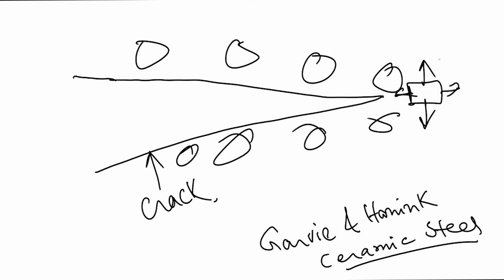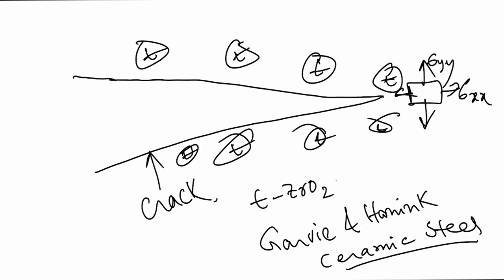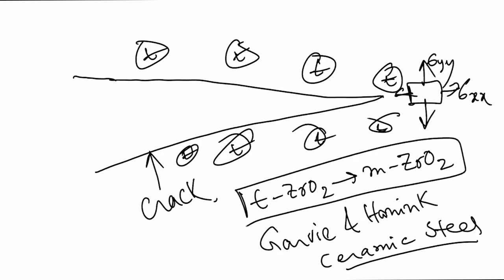Now in the crack tip stress field, suppose this is sigma xx, this is sigma yy and all. Suppose in the crack tip stress field, this is your T phase, tetragonal zirconia phase. If tetragonal zirconia phase transforms to monoclinic zirconia, I am just trying to explain to you, tetragonal zirconia has always a desire to transform to monoclinic zirconia phase.